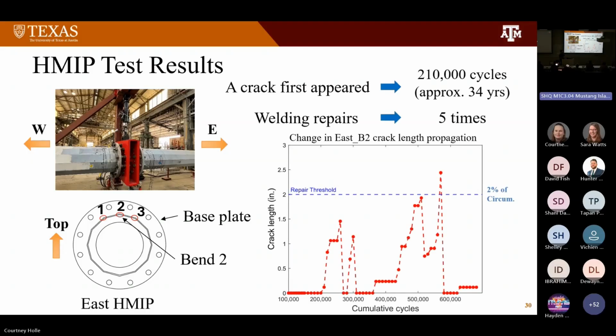The chart on the right shows the crack length propagation at East HMIP Bend 2 over the cumulative cycles. The x-axis represents the cumulative cycles, and the y-axis represents the crack length. The blue dashed line is the repair threshold at 2% of circumference. That is 2 inches.